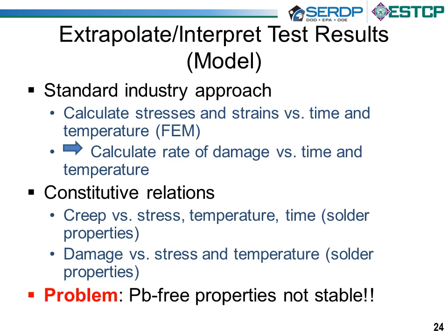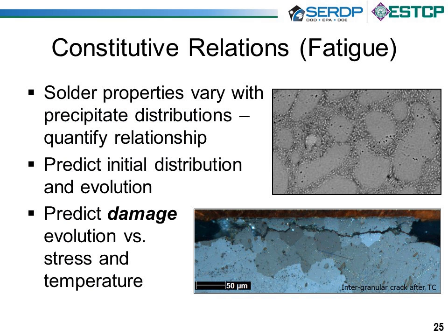And the problem we're up against now is that for lead-free, the properties of the solder are not stable. They weren't totally stable for tin-lead, but it was not a serious or critical problem. For lead-free solder, that's a big deal. So what we're up against, and we did the research to support that, is that the properties of the material are determined by two different aspects of the tin material, which is the basis of the solder here. Okay, it's 97% or so tin, and then there are some particles, some precipitates in it.